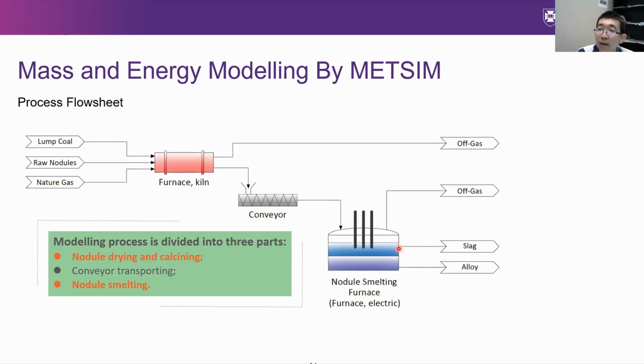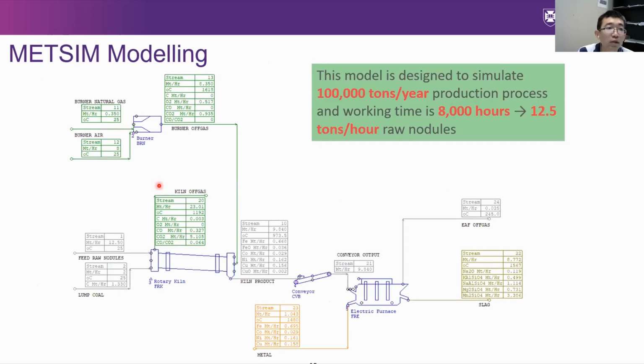And then we use the METSIM software to model the mass balance and energy distribution in this nodule treatment process. This is a simplified process flow sheet referring to the laterite smelting process, which mainly contains the rotary kiln furnace for the nodule drying and calcining, and then the feed goes to the electric arc furnace for the smelting reduction. Here I use natural gas as the fuel source for heating. And this is the METSIM modeling result of the flow sheet.